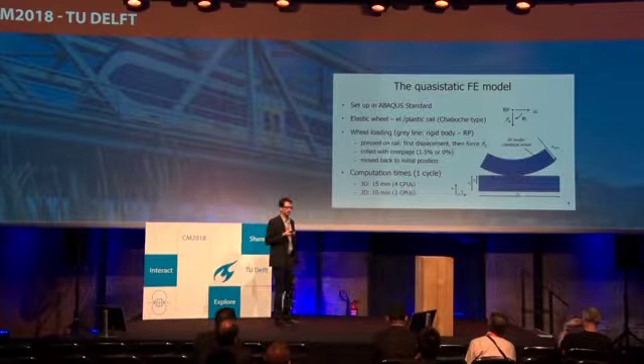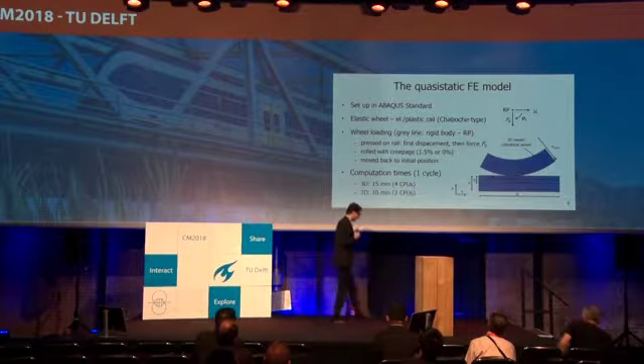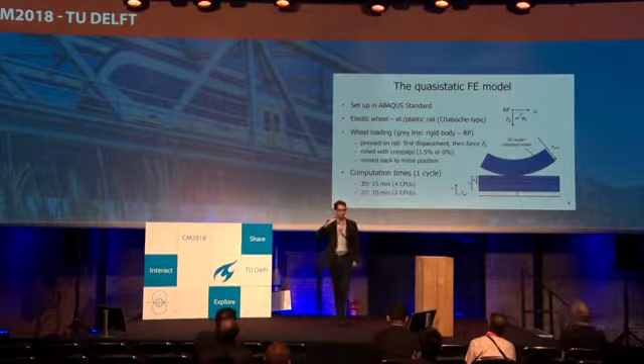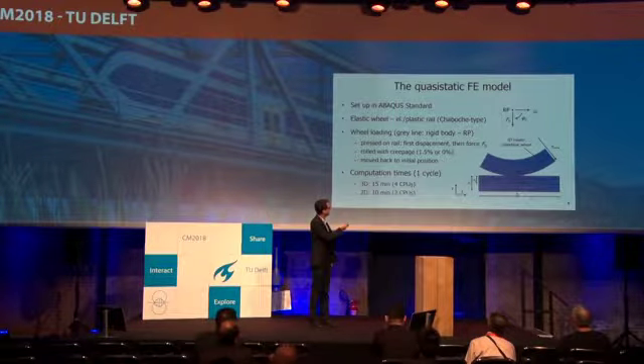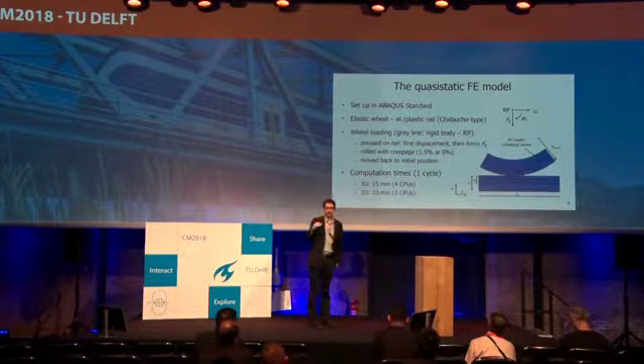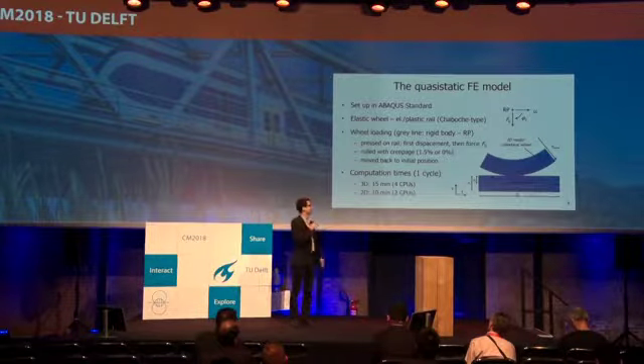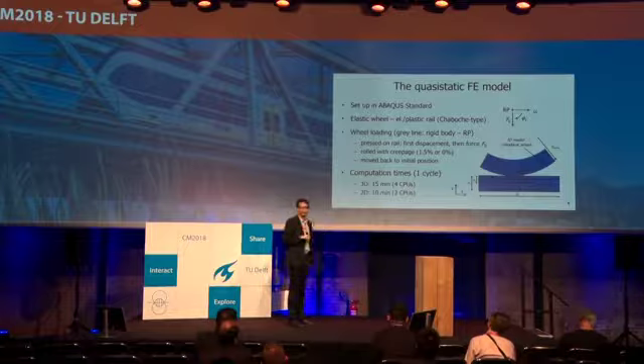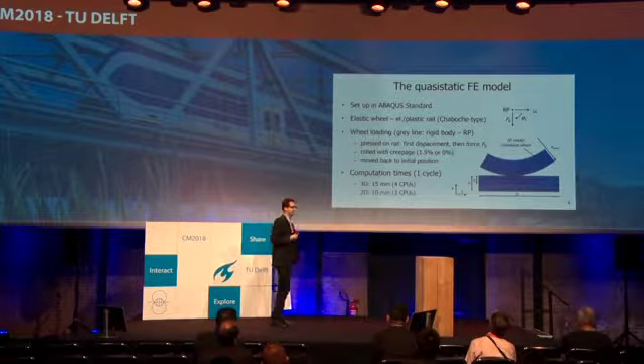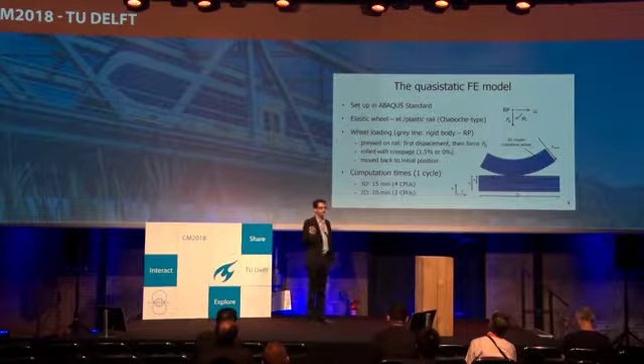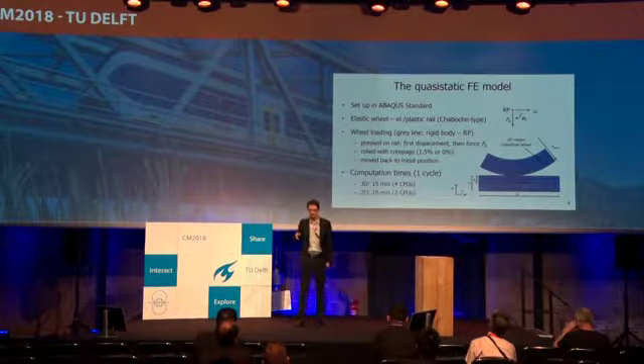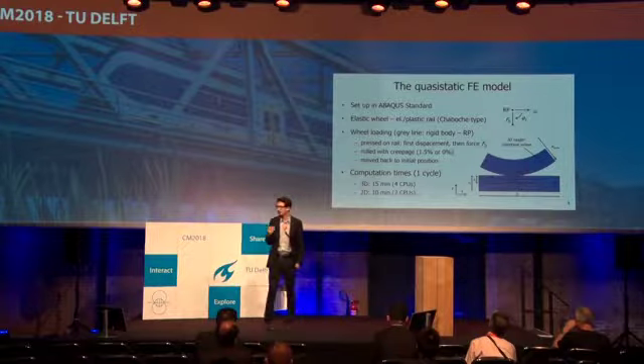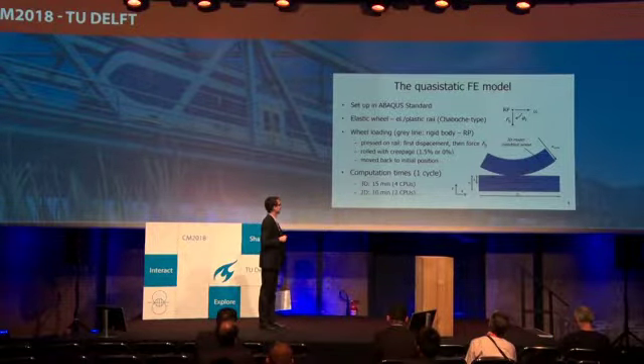What you don't see here is the 3D model. It could be really 3D, and at that point, we investigate loads where we have a conical wheel. While we're doing that, the voestalpine test rig can be set up to have a cylindrical wheel, which is rolling on the rail head. And then they can apply a slip, for example, 1.5% in an accelerating movement, and then they actually already measured plastic shear deformations for, I think, 700 cycles, 1,400 cycles, and many more cycles. So that would be our means of validating that.